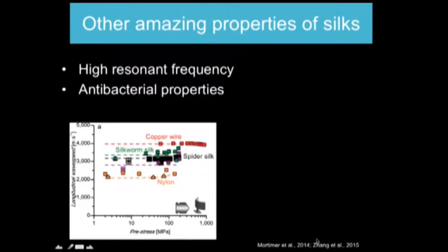Now, spider silk, such as, again, dragline silk, has many cool properties that we're only recently starting to uncover. One of which is the high resonant frequency of spider silk. And this is interesting for engineers and material scientists, but also for biologists studying zoology. If we look at this left graph, because I know it's a lot of information to present on just one slide, you can see spider silk here along with silkworm silk that have this longitudinal wave speed near 3,000 meters per second. Longitudinal wave speed is the speed at which vibrations travel through a material from molecule to molecule.